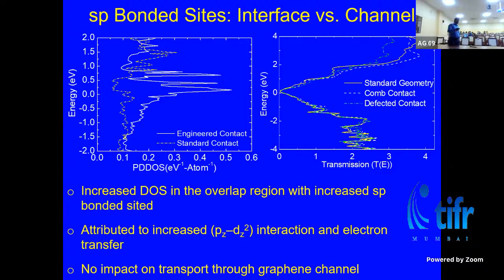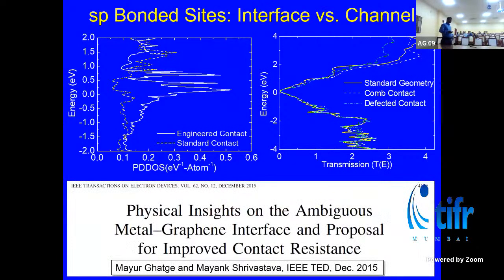And for this system, if you just study the transport across the channel, you see the transmission probability does not change, which means no matter what happens in the contact area, nothing changes in the channel region. We are not introducing defects in the channel region, and also the contact area does not influence the channel region. The channel region is intact. That's what we want. We want the intrinsic properties of the materials to be harnessed through the channel region. So we want the channel region to be intact.